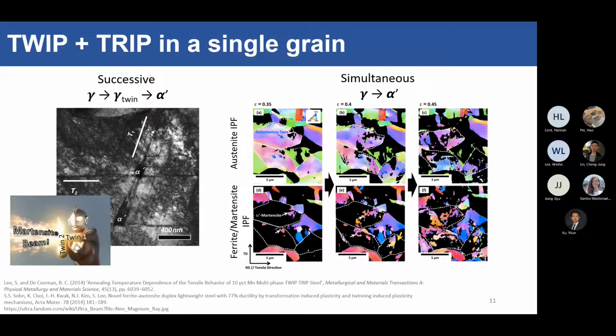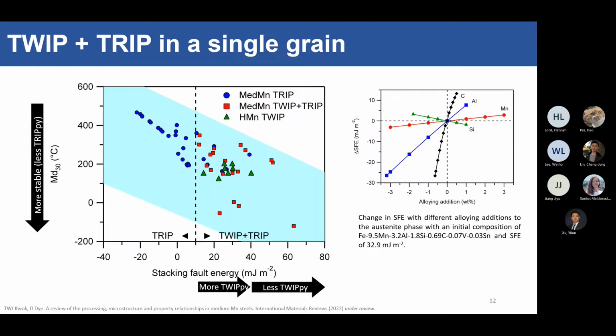So the other way to form TWIP plus TRIP is the simultaneous effect. And what that means is that your twins and your martensite form together independently of each other. There is no relationship between the twinning and the TRIPping together. Okay, so there are two ways to form this TWIP plus TRIP mechanism.